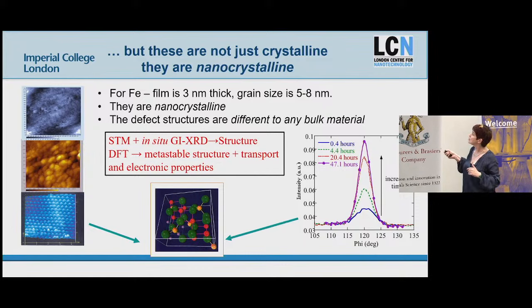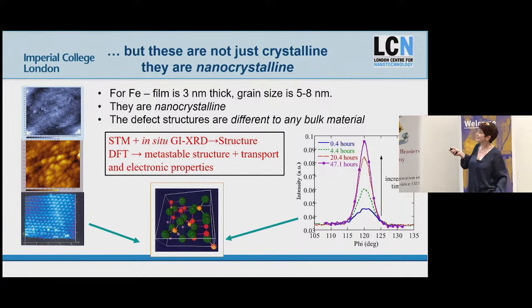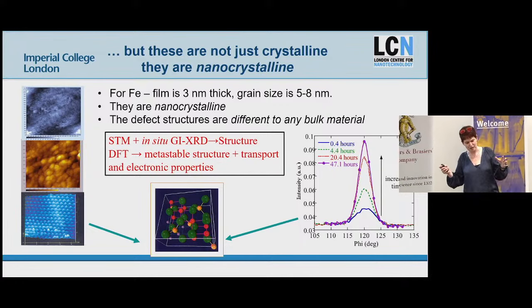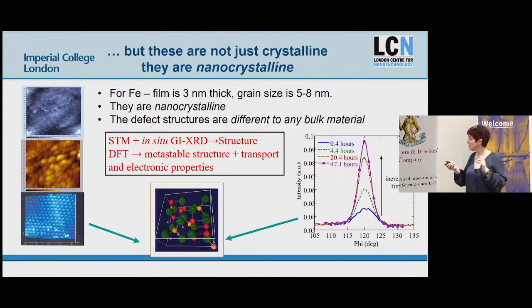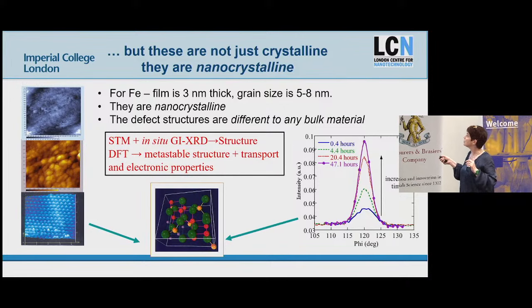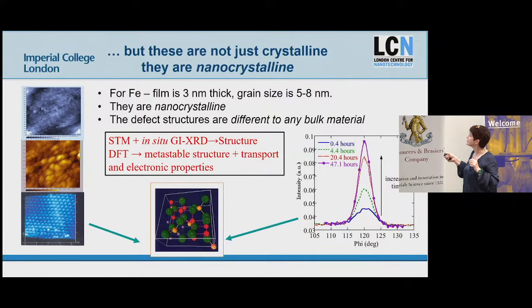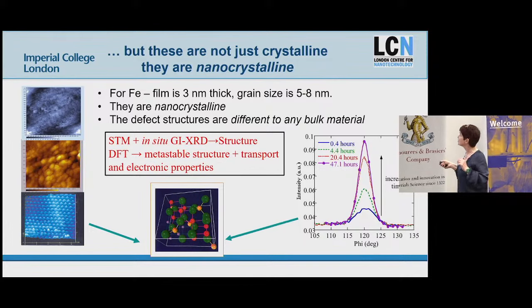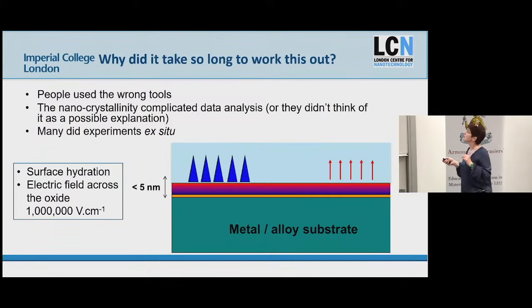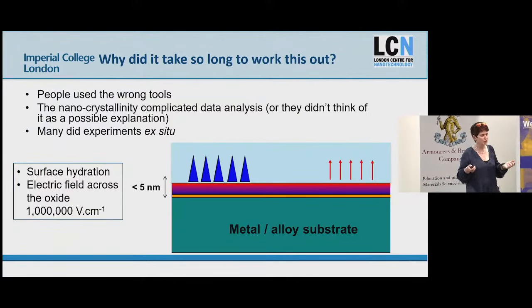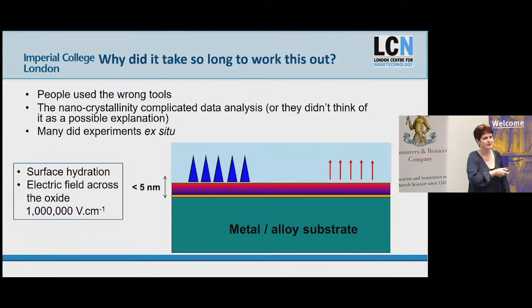And then we were able to do some in situ X-ray diffraction measurement. This is an X-ray diffraction peak. It's the 004 peak, if you want to know, of the spinel structure. And we were able to see in situ, so in an electrochemical cell, the film growing. And this peak width here, materials people recognize, tells us that it's nanocrystalline, and we can see how it grows with time.